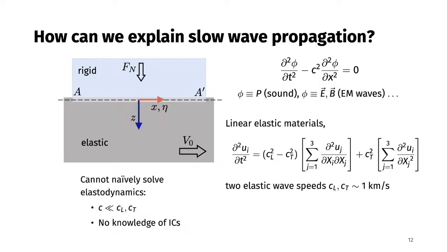This is a rubber, yes. There is also a viscoelastic time scale effect. They are lower, yes. So this one is hardened, so the cross-linking density is higher. So it's about 800-ish meters per second. So it's order of magnitude, right? But typically, if you have a very flexible rubber, you're looking at a couple of 100 meters per second.